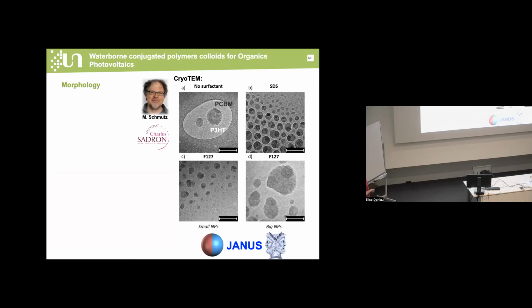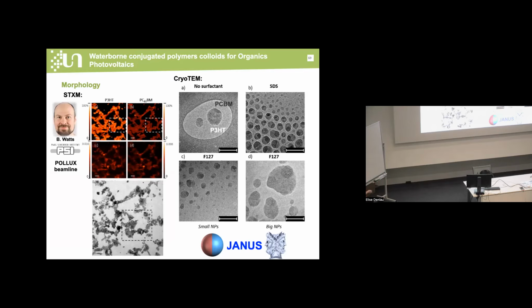centrifugal dialysis device. So then we characterize the morphology of the nanoparticles by using cryo-transmission electron microscopy together with Mark. And we could see for the first time a Janus morphology of nanoparticles of semiconducting materials. And this Janus morphology was also confirmed using STXM at the Pollux beamline with Benjamin Watts. And here it was a bit difficult to characterize by STXM because the nanoparticles are rather small. However, we could see several high contrast stripes, which is more in accordance with a Janus morphology than a core-shell morphology. But this shows how powerful cryo-TEM is to show the morphology of a nanoparticle, because we could see this Janus only using cryo-TEM.